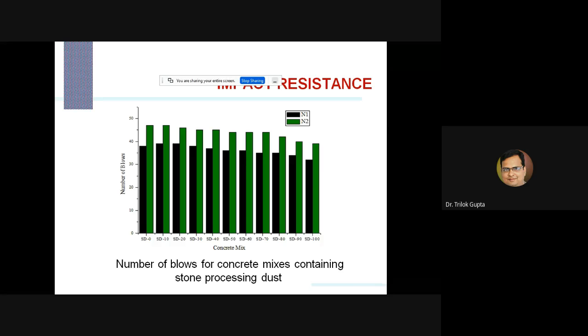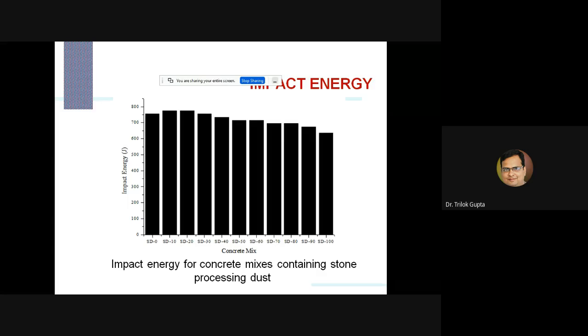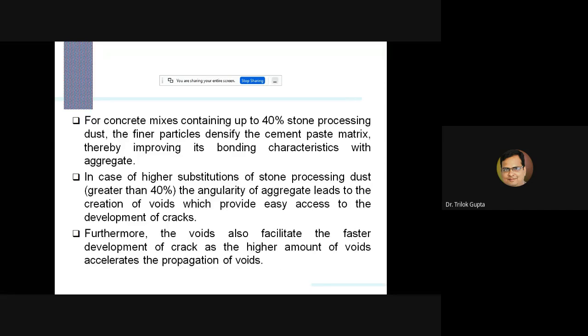But for concrete mixes containing stone processing dust higher than 40%, the number of blows, or we can say the impact energy, is less than the control mix. So we can observe that after 40%, there is a decrease in the impact energy. This impact resistance of concrete depends on the paste-aggregate contact area and bond, how stiff the bond is, and a solid concrete matrix enhances these properties, which are instrumental in resisting the propagation of cracks.